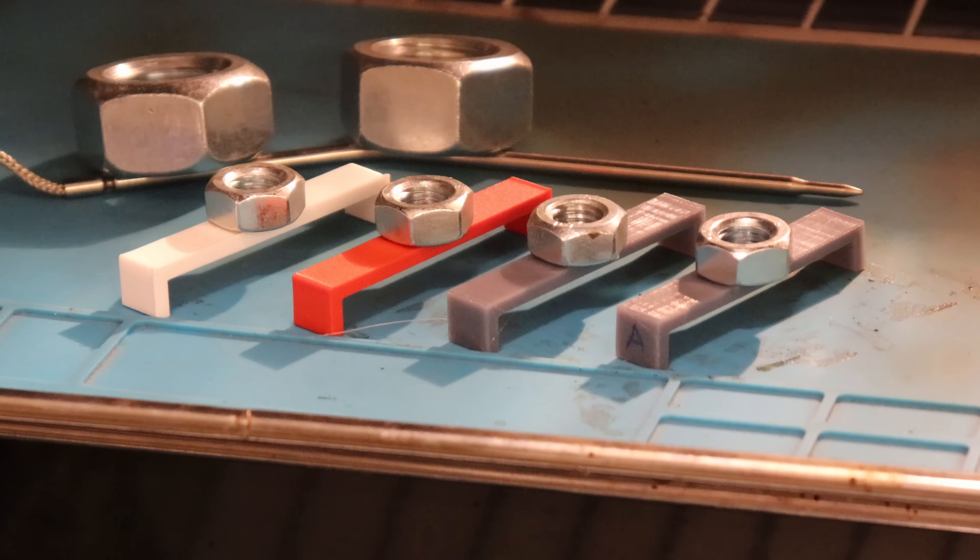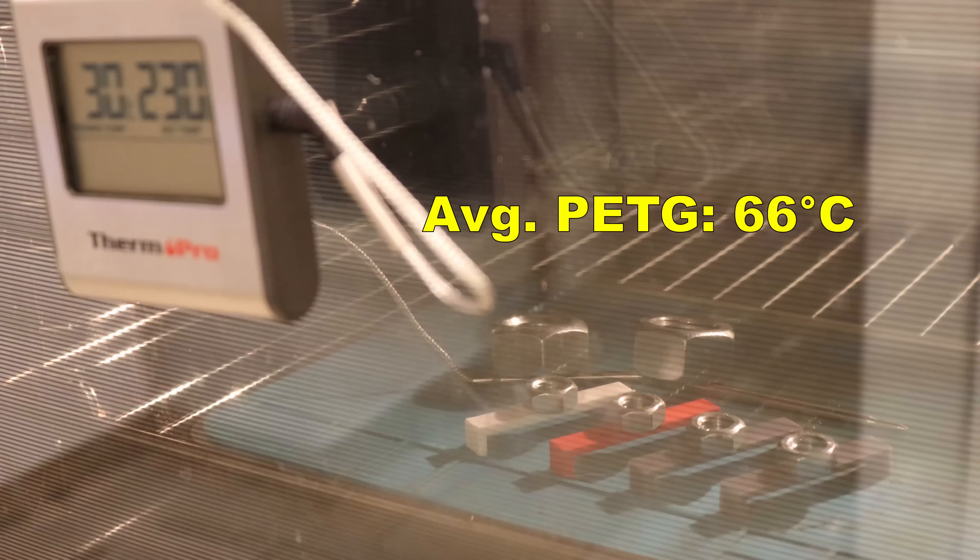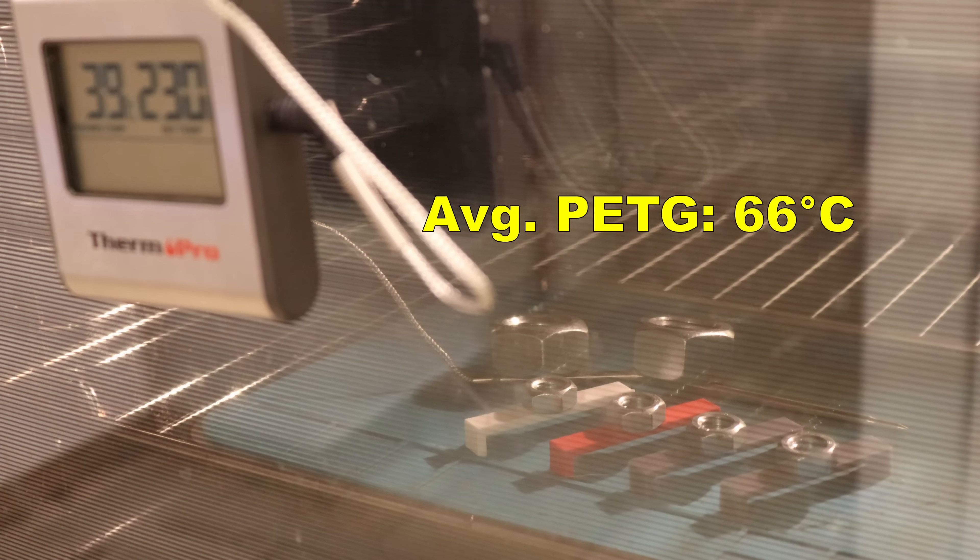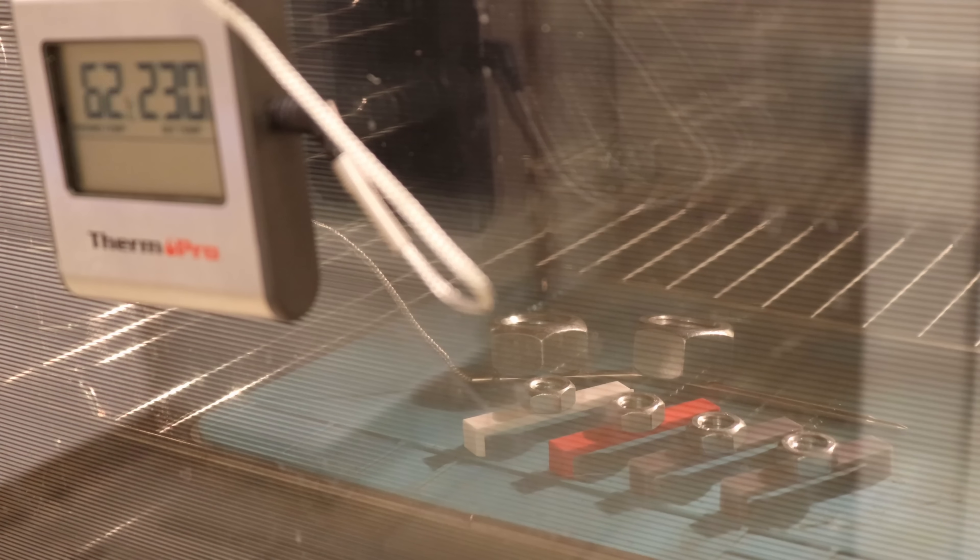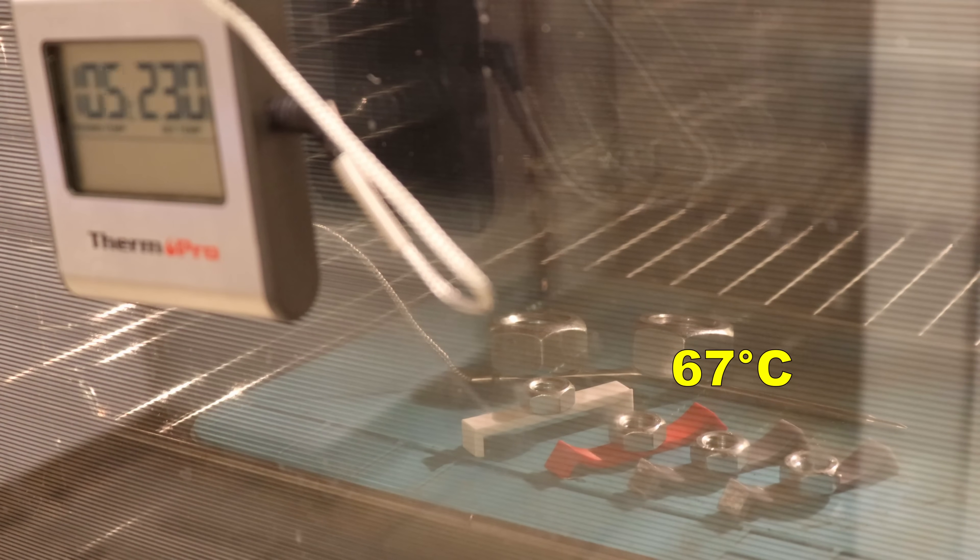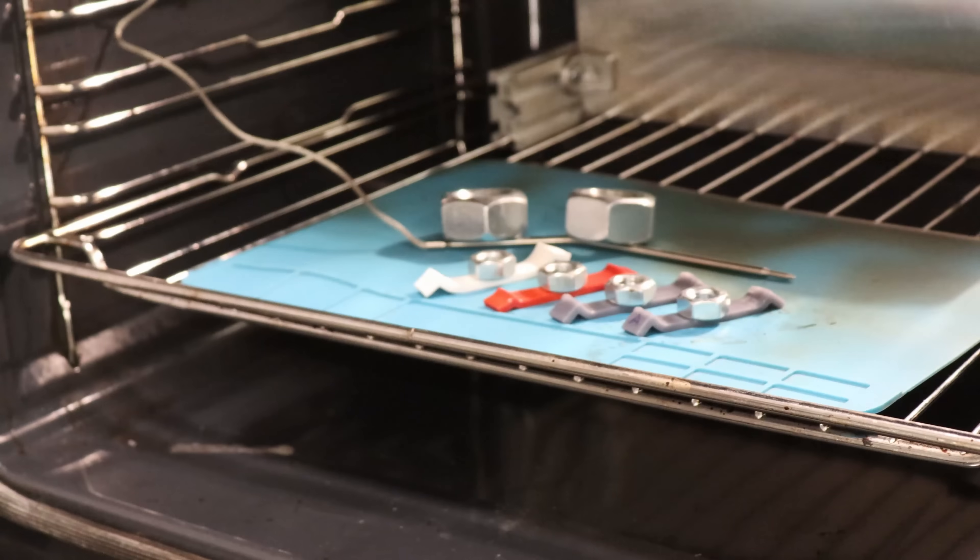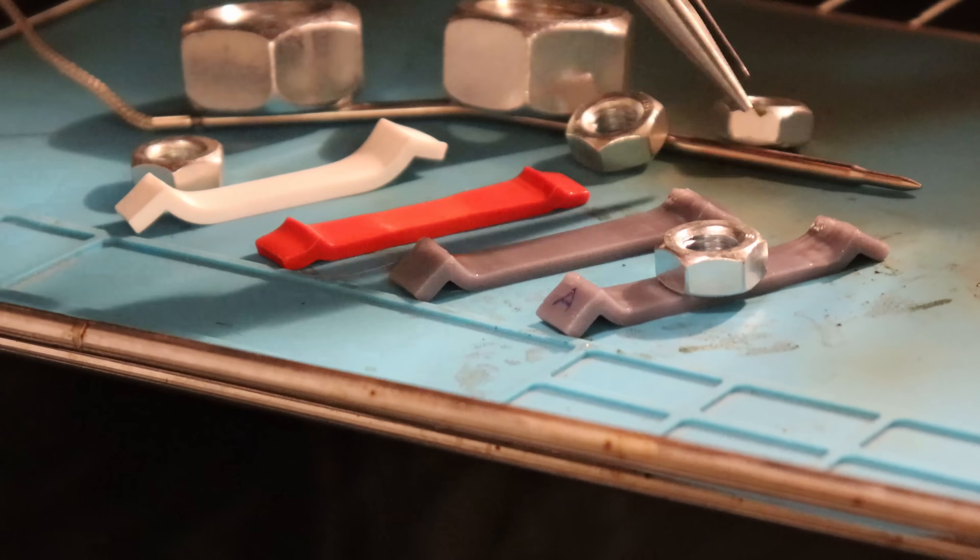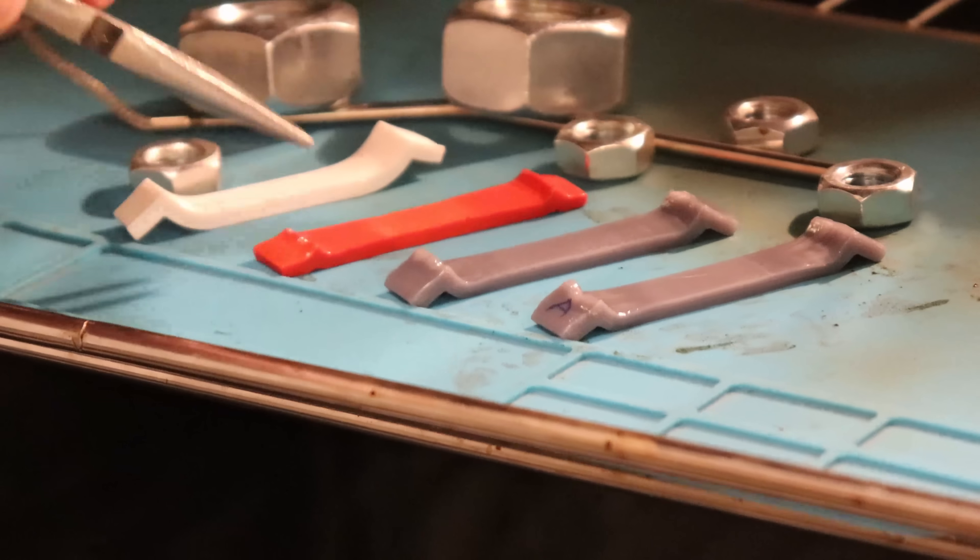Temperature test in the oven, and I have several tests in progress. This is sped up timelapse video. And this Spectrum PETG started with deformation at approximately 67 degrees Celsius. And because of that white PC ABS, I ran the experiment up to 160 degrees Celsius. And of course, at this temperature, this material became too soft.